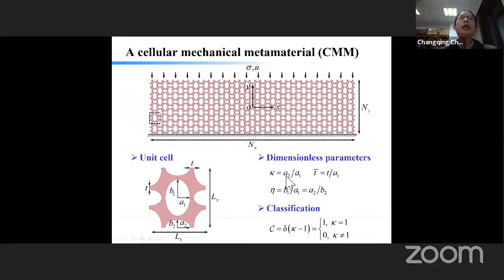Here kappa is the ratio between A2 and A1. T bar is the ligament width shown here, and A1 and B1, A2 and B2 are the semi-axes of the bigger elliptical hole and the small elliptical hole. Remember this parameter kappa is very important, because we consider it plays a dominant role in what we are going to show you. So we define a parameter C: if kappa is one, C is one. If kappa is not equal to one, then C is zero.